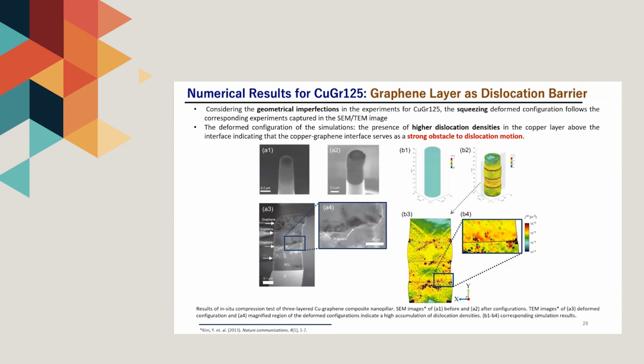As shown in the TEM image A4, in the deformed configuration of the sample, a high accumulation of dislocation density is identified above the graphene layer. The simulation results well matched the distribution of the dislocation density.